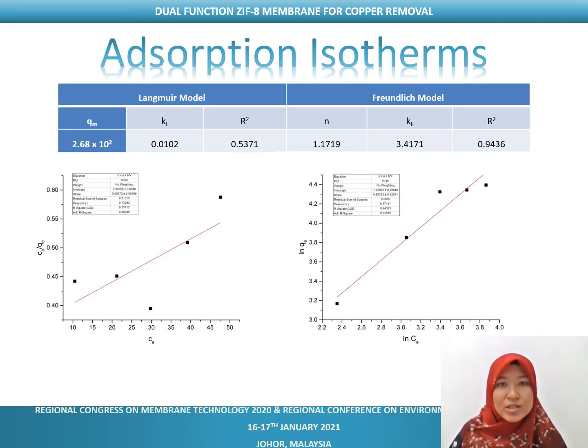Next are the results of the batch adsorption study for the ZIF-8 membrane. The table shows the adsorption data analyzed via Langmuir and Freundlich isotherms. From the data obtained, the adsorption mechanism of copper-2 onto the ZIF-8 membrane was best fitted with the Freundlich model, as the R2 value is higher than the R2 value of the Langmuir model. The Freundlich model suggests that metal ion uptake occurred on a heterogeneous surface by multilayer adsorption. The slope, 1/n, implies the adsorption intensity or surface heterogeneity of the adsorbent. The surface is more heterogeneous the closer its value is to 0. In this study, 1/n equals 0.85, which implies less heterogeneity of the ZIF-8 membrane surface.